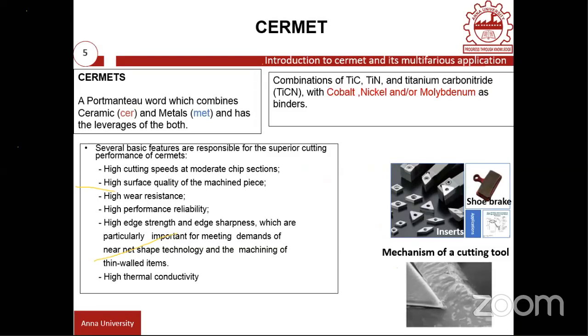CERMET has several good features. One, high cutting speed at moderate chip section. When the chip section is very moderate, the force required to separate the chips will be much lesser. That means the frictional heat developed at the chip-tool interface, the temperature generated because of the rubbing action of the chip, would be very minimal. So with minimum chip thickness, you have benefits. High surface quality of the machined piece, improved surface roughness value, and also high wear resistance. As a result, the tool life of these CERMETS is really commendable, along with high performance reliability and high edge strength. One important aspect is the edge strength, that is, the rupture strength of the cutting edge.